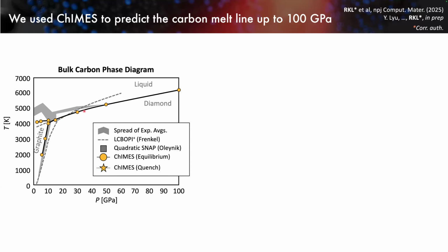What we're looking at here is our diamond portion, and we are actually consistent with the experimental data here. Our graphite portion is also low relative to the experiments I'm showing, although the slope is doing a little bit better. We have some questions about whether this is an effect of how we ran our simulations or not, but still a fairly good prediction here.